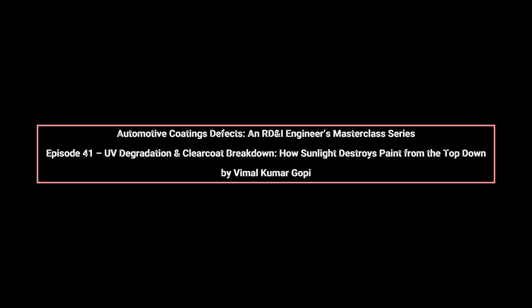Crosslink density strongly influences degradation behavior. Highly cross-linked clear coats resist early gloss loss, but suffer brittle failure once degradation reaches a critical point. Less cross-linked systems degrade more gradually, but may lose hardness and mar resistance earlier. OEM formulations carefully balance these behaviors to achieve controlled, predictable aging.